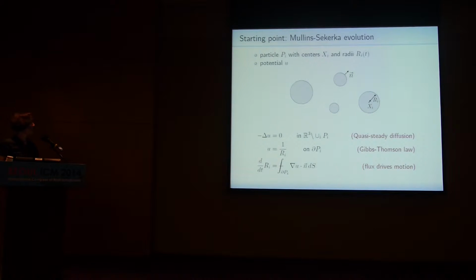Okay, so I said we have as a starting point a well-established continuum model that we do not want to discuss, so this is the truth, if you want. Here in Ostwald ripening, the model is known in materials science as the Mullins-Sekerka free boundary problem, which is as follows. We have three dimensions. You can think of a large cube in three dimensions or just particles uniformly distributed in all of R3.